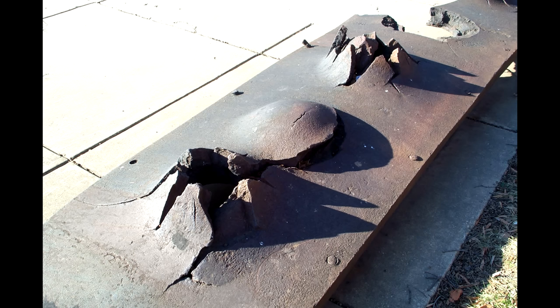The iron would peel back, there would be a small hole, just a fraction larger than the projectile, as opposed to a big gaping hole with lots of splinters, as would be caused by shot passing through a wooden hull. And thus, the overall effect was considerably less, and a small neat hull was much easier to patch as well.